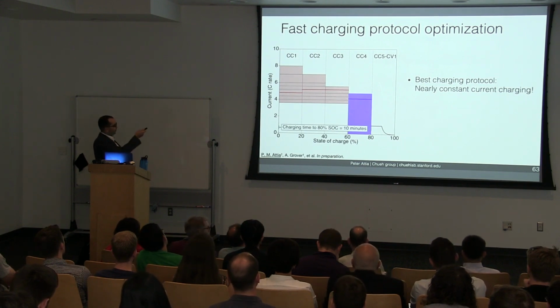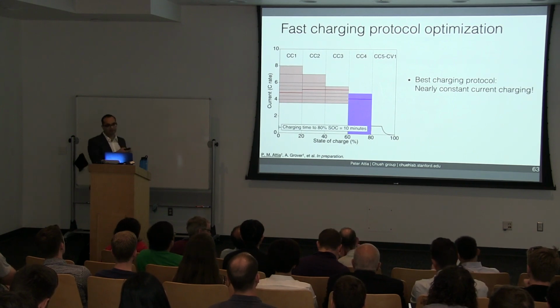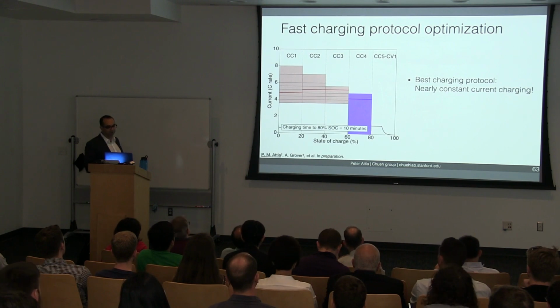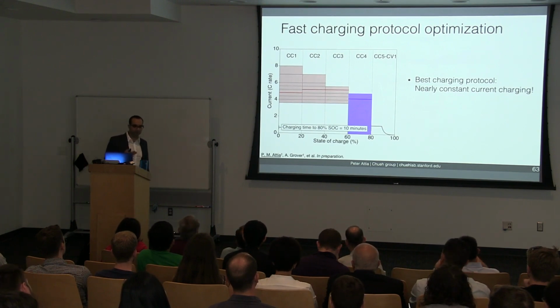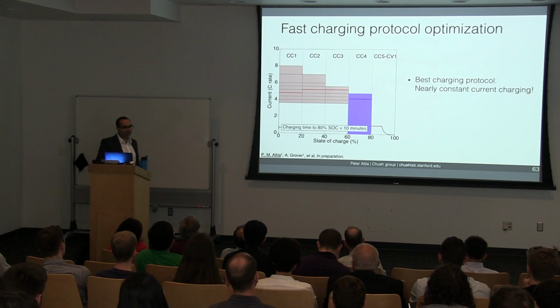If you look at the best protocols estimated by OED, we find that this charging protocol is very close to constant current charging. This is quite different from conventional wisdom of fast charging optimization. Again, most charging protocols proposed in literature have monotonically decreasing currents to avoid plating. So the natural question becomes, what degradation mode are you optimizing for with charging?